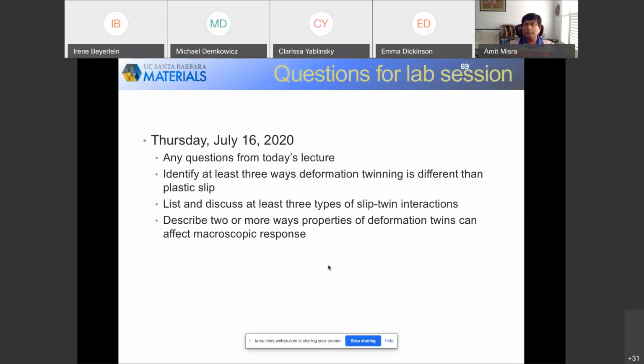But when twins happen, theoretically you could identify when they happen, though you would need a certain threshold of volume before you can identify how much twinning you have. The rule of thumb is that once the volume fraction of twins is over about 15 to 20%, then they can be detectable.